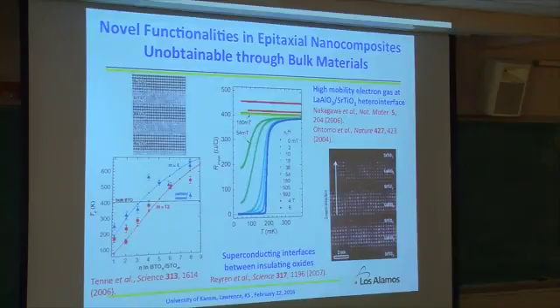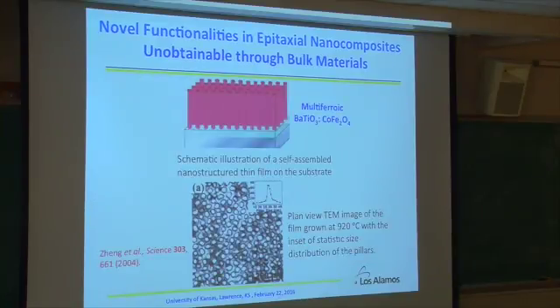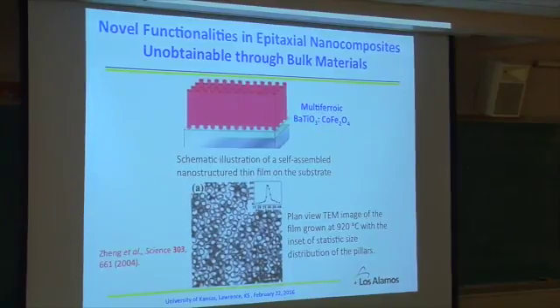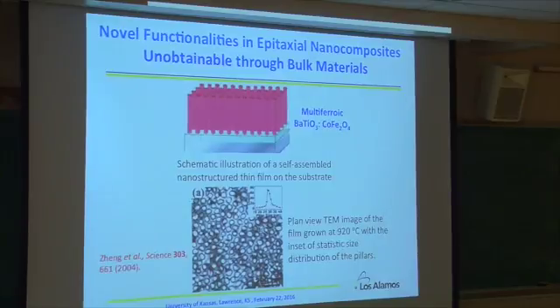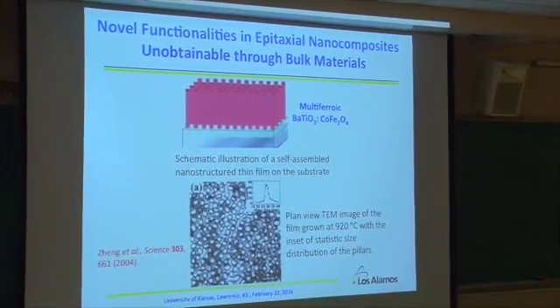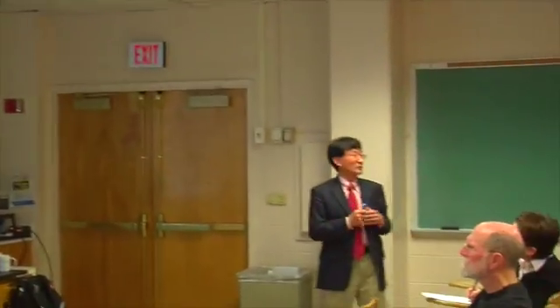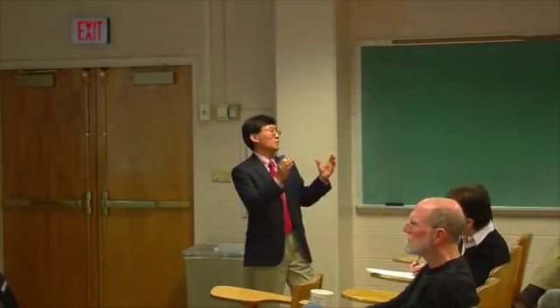One more example from others, and then I will show our work: a pillar structure, like barium titanate and cobalt ferrite. Barium titanate is ferroelectric and has the electrostrictive effect. Cobalt ferrite is a ferromagnetic material. When you couple these two together, this is just the top view, you look at the pillars and you have this kind of structure. You form a nanocomposite material with a new magnetoelectric property, the ME effect. You really form a functionality you don't get from either single phase.